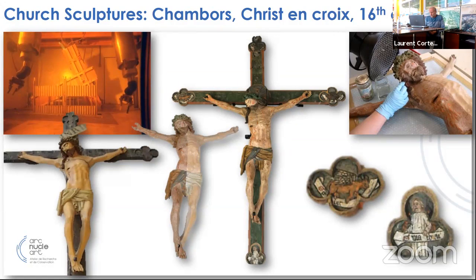After that takes place the restoration. You can see in this case of this crucifix on the cross from the 16th century, it was previously covered with thick and heavy resin paint, and we do what we call the painting removal to go to another layer of painting that was very nice and more interesting. This is typically what we can do in our workshop.